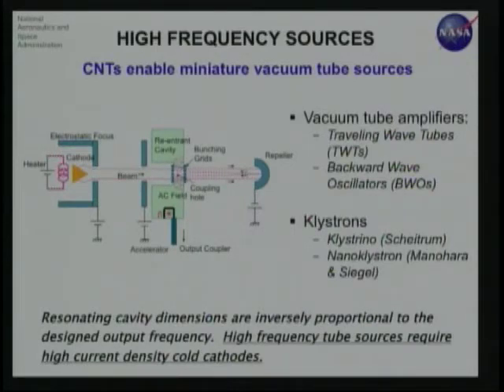So with such a source, as the frequency increases, the dimension of the device decreases proportionally, but the current requirements, also current density requirements, increase. So you need a very high current density source. And you cannot use thermionic emission, because if your entire device is about a millimeter by millimeter square, it's very hard to fit a thick thermionic source to it. So you are forced to work in the cold cathode regime, or the field emission regime.